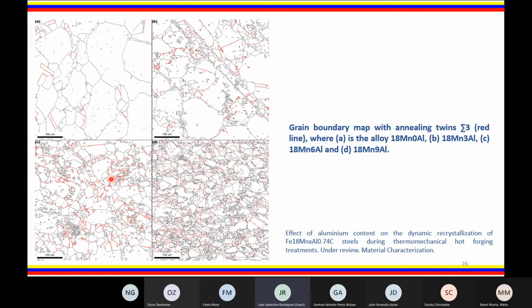In the case of high aluminum content, the increase in the content of this element for the composition of iron, 18 manganese, 9 aluminum, 0.74 carbon steel will favor the formation of a second phase. In this case, it is ferrite. Therefore, the grain refinement for high aluminum composition ends up being the joint action generated by the difference in dislocation densities, the nucleation dynamics of a second phase, that is, of the ferrite, and chemical segregation generated by spinodal decomposition. Once we have this work published, it will be a pleasure to share it with you.